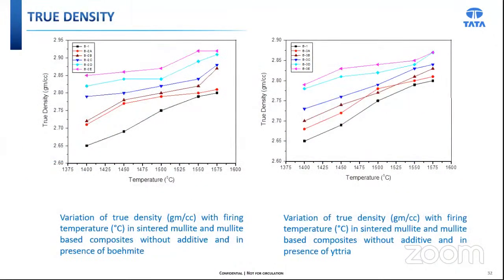Now coming to the true density. Since mullite possesses lower specific gravity than corundum, with an increase in the alumina content or alpha alumina or corundum in the sintered compacts through the incorporation of boehmite, the true density of the sintered body is likely to increase progressively with rise in temperature.